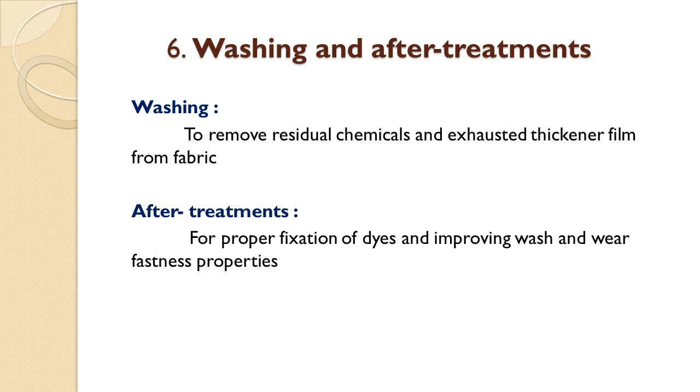In case of reactives, initially after steaming we may go for washing to remove the hydrolyzed reactive dye, to remove the exhausted thickener film, followed by soaping with 2 GPL non-ionic soap at boiling condition. So this is how the after treatments are dependent on the type of dye which we have used for printing.